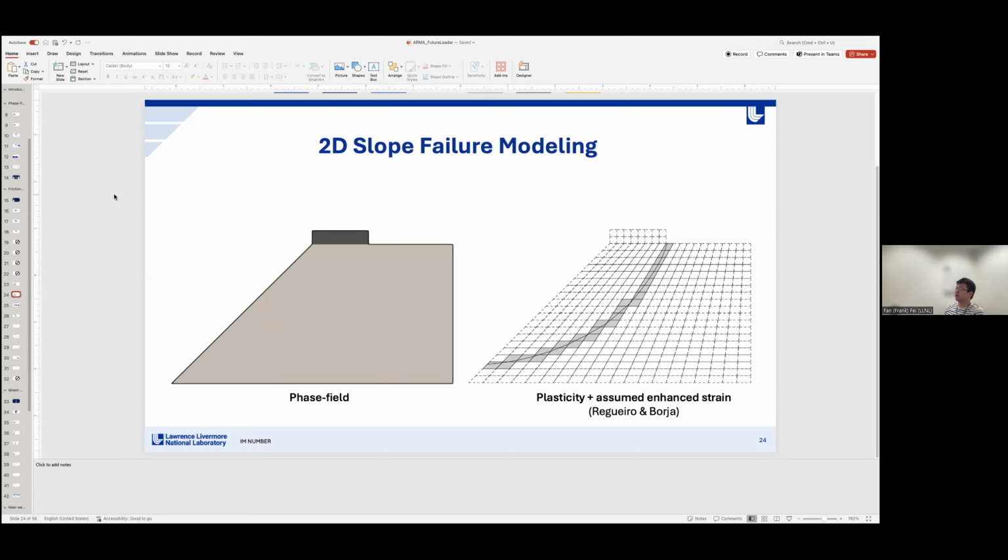That's why they are also showing interest in using the phase field for earthquake modeling or for fault growth and fault mechanics problems, because it's better than the plasticity method, since plasticity doesn't essentially change the elastic properties. But the phase field actually adds this degradation on the elastic stiffness. So yes, you can understand it in this way.